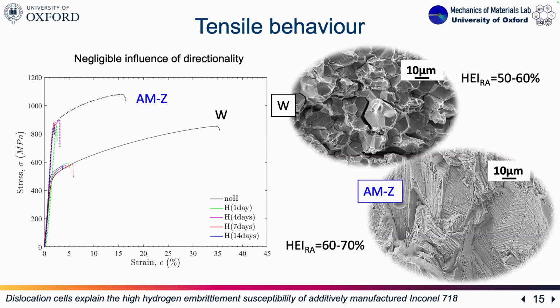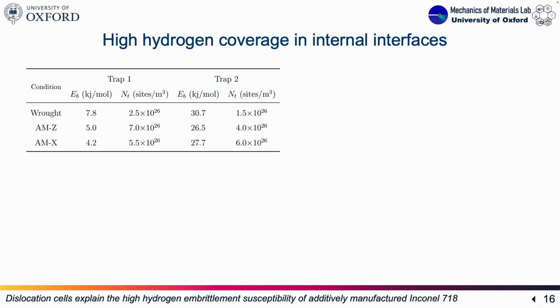So basically, we are having accumulation of hydrogen along these interfaces. We could explain these results on the basis of the trap binding energies that we have measured, these lower binding energies in the additive, and also the faster diffusivity. This indicates that hydrogen is accumulating in the high dislocation density of our cellular structure, and that is provoking a higher absorption of hydrogen, and also a reduction of the binding energy, because we have pipe diffusion along this cellular structure, which is also related to the higher hydrogen diffusivity in the additive.